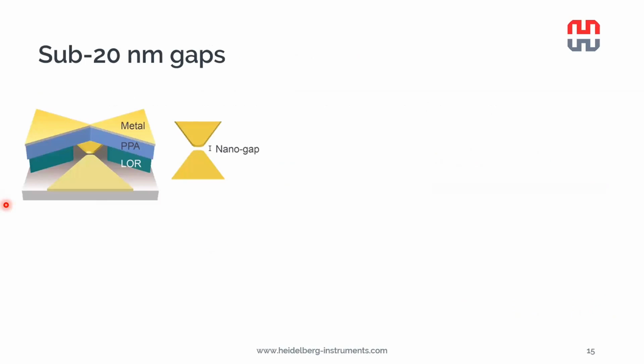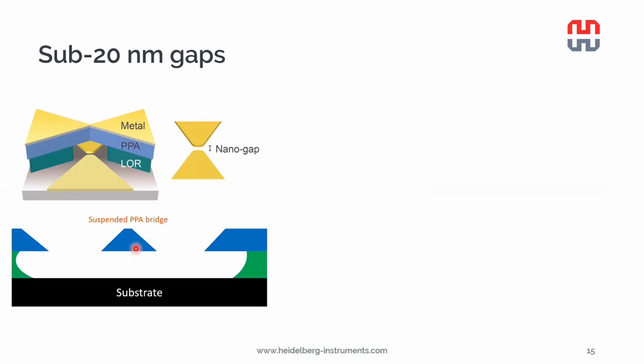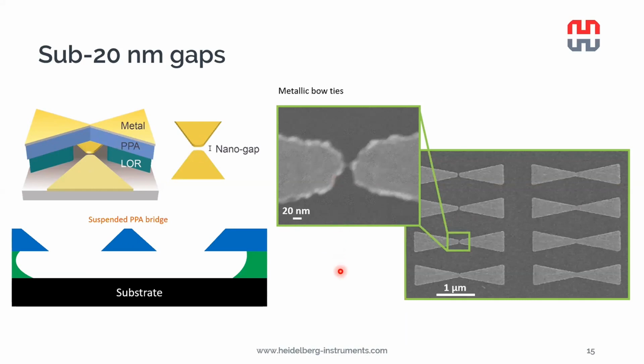But such freestanding bridges can also be taken advantage of for certain device architectures. Namely, the suspended PPA bridge, if it's made short enough, can support its own weight, and it can be used as a shadow mask for evaporation, as explained here. So here the PPA bridge is supported by the LOR islands on both sides. The undercut has completely removed the LOR here in the middle, and what we are left with is this kind of nano gap structure, which is defined by the PPA bridge. Using this approach, we have achieved to pattern less than 10 nanometer nano gaps between metal electrodes. Very useful structures for example for plasmonics devices.